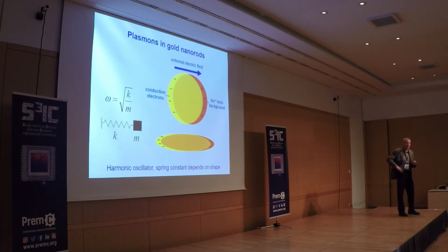And who says surface density of charges says electric fields. So there will be large electric fields in the vicinity of the surface of the nanoparticle due to these surface charges. If in addition to this metallic property you play on the geometry of the particle by taking an elongated particle as a nanorod here, which I sketch as an ellipsoid, the surface density is even larger. You see that the number of charges per unit area is even larger in the case of a rod than in the case of a sphere, which means that this surface electric field will be even larger. And you can take benefit of this to enhance interactions with objects and to use sensing properties.